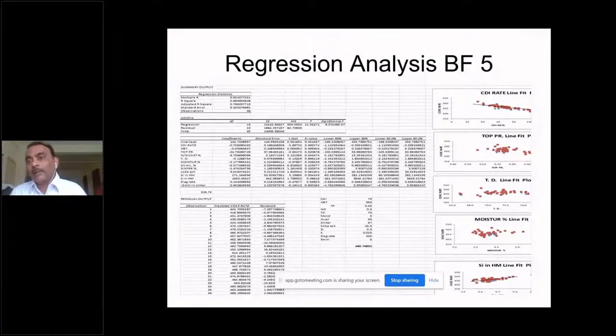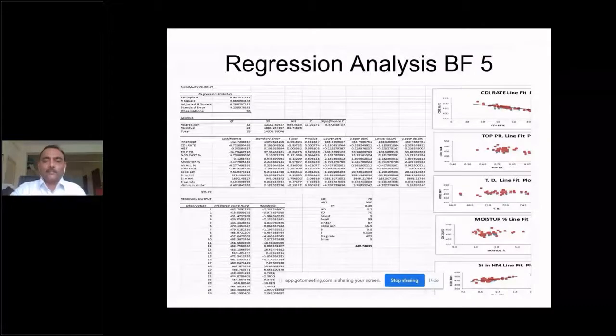But when you do the multiple linear regression, in which you get one value, maybe coke rate or productivity, there are so many factors. As we are seeing, there are more than 2000 factors. But the main 10, 15 factors we will take for the regression analysis from the data of blast furnace 5 of 3 years. And when we put these values and did the regression analysis, one very nice thing happened.